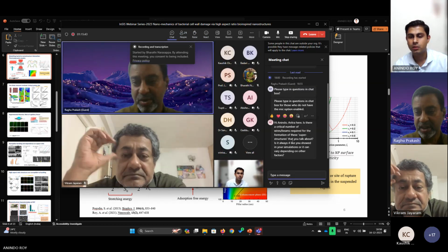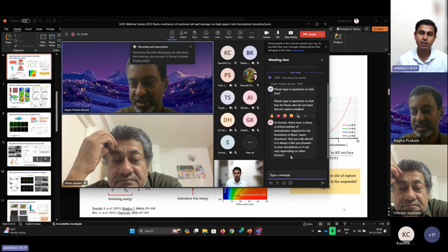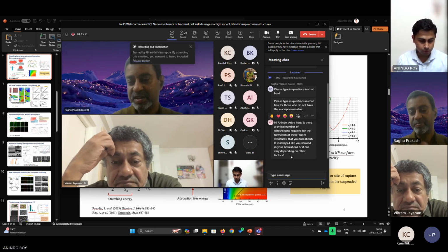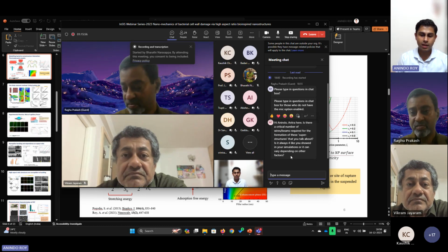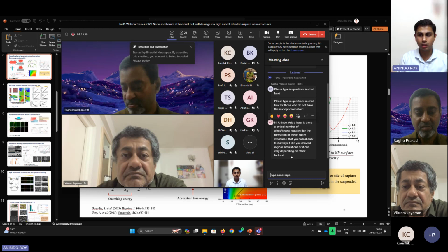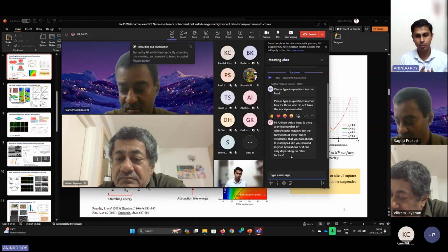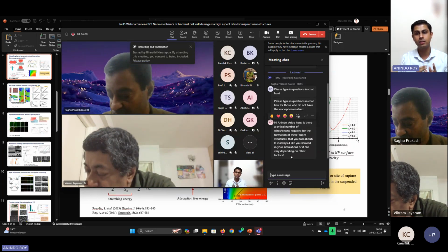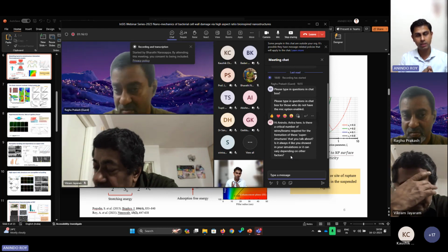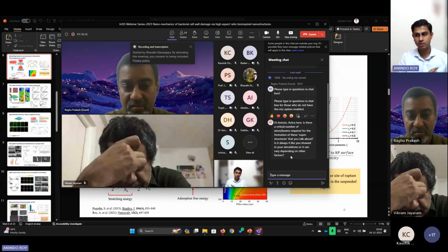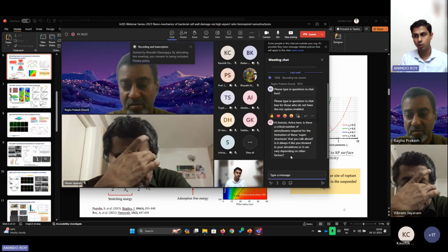He's talking about the critical number of wires or beams required for the formation of the superstructures. Right. So there is no critical number as such. It is just that if your pillar interspacing is not too high, it allows the pillars to interact with each other through electrostatic interactions or capillary forces or van der Waals forces at the pillar tip. And if your pillars are not spaced too far, then they will come together to form superstructures.